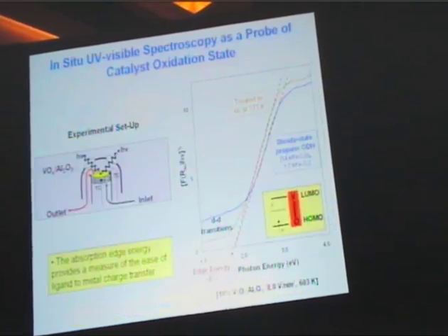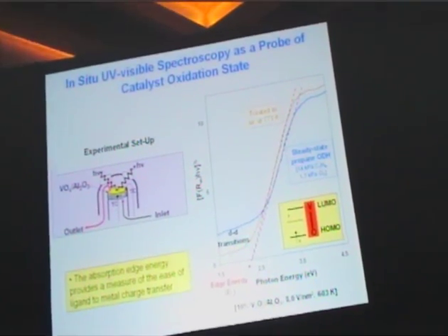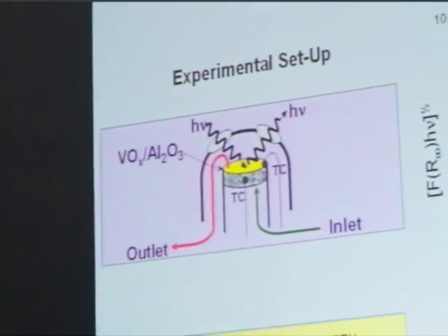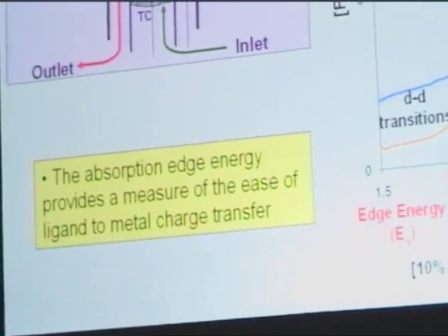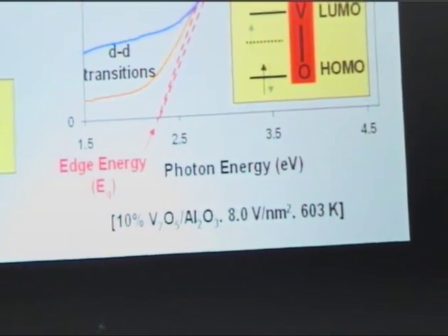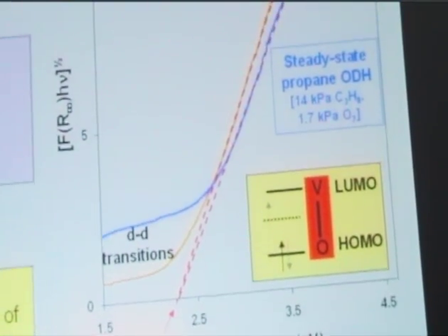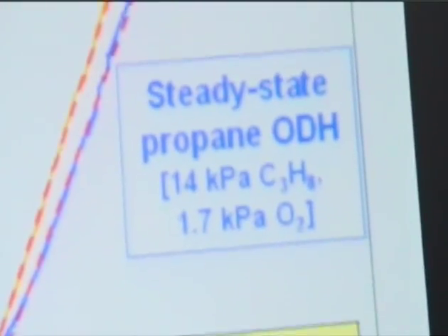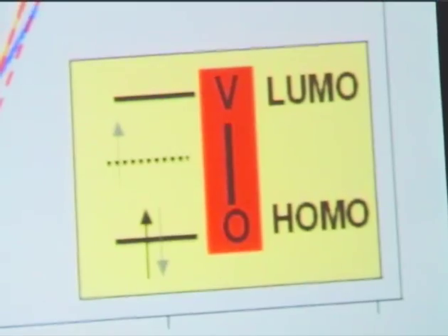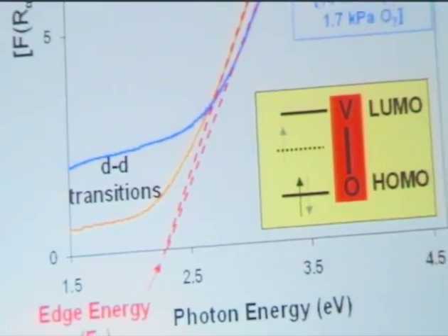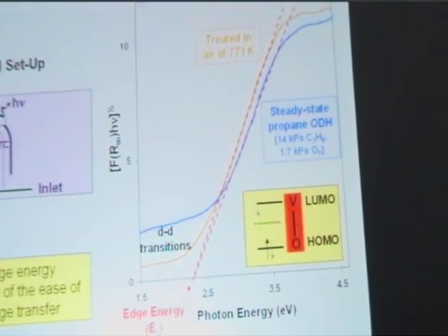Now, we wanted to understand why the rate changes as we change the loading. And so one of the tools that gives you some insight is UV, ultraviolet, visible spectroscopy. And this has been practiced in our laboratory in situ. Here's a little cartoon of a cell, a little bit of catalyst here. Photons come in, they're scattered off this catalyst pellet, and then out for analysis. And what we see is this kind of spectrum. And if you extrapolate the linear portion here back to zero, you get what is called the energy band gap,